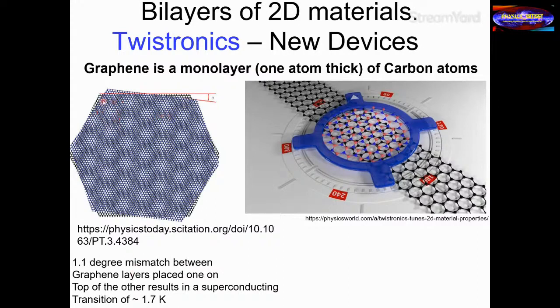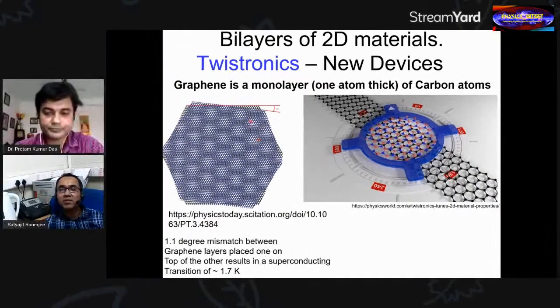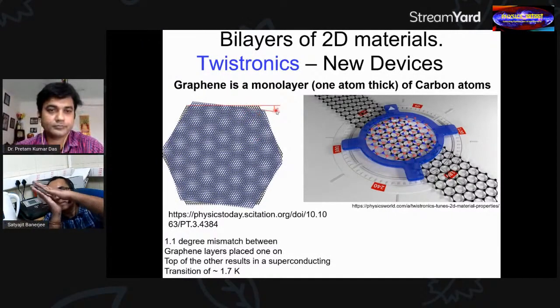Okay, and if you take these two sheets of carbon atoms and place them one on top of the other and create a mismatch of 1.1 degree, this is the honeycomb lattice that you can see of these carbon atoms. If these two sheets are actually twisted by 1.1 degree, then superconductivity is found to emerge inside this bilayer of 2D sheet of materials. And the transition temperature is of course very low. The superconducting transition is 1.7 Kelvin.